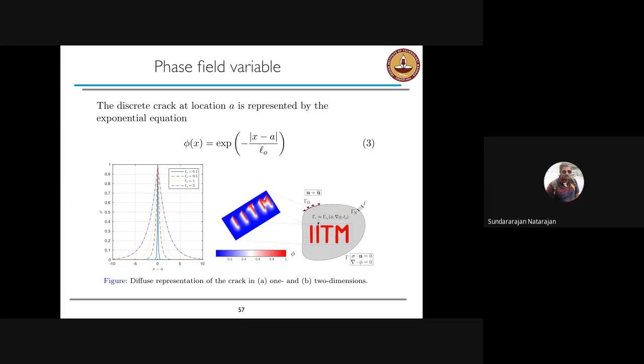Now the question is, how do I go from 0 to 1? There are different ways by which you can do it, and typically we use an exponential to represent it. To be able to model the width of the crack, we have this parameter called L0 that dictates how sharp or how wide the crack is. The larger the value, the thicker the crack, and the smaller the value, the sharper the crack is.